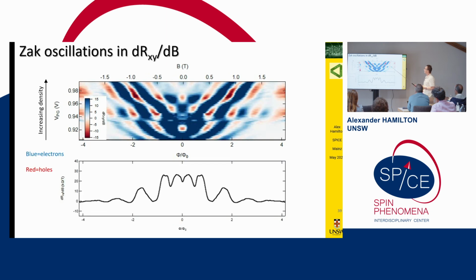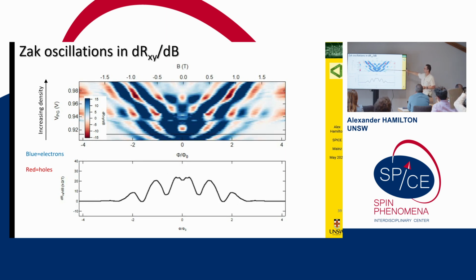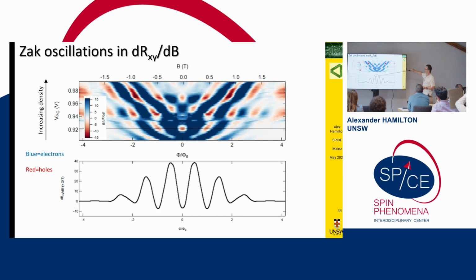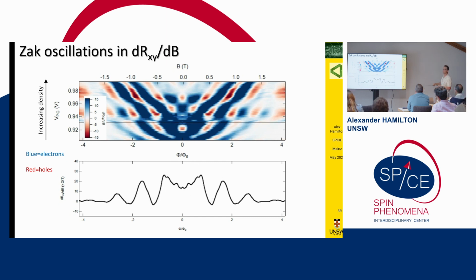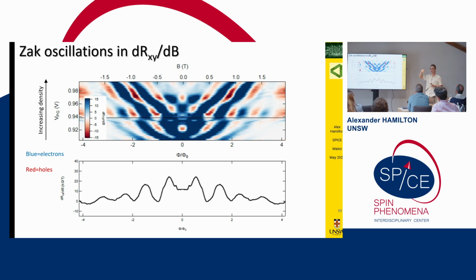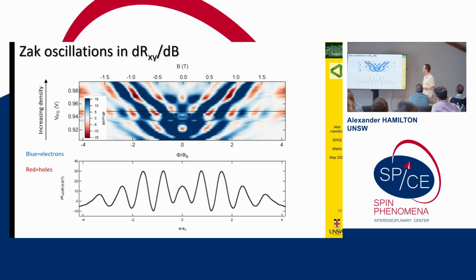You can see it a bit more clearly if I just take the derivative of the Hall voltage as a function of magnetic field. And again, I start down here, and then here I'm plotting the derivative as a function of magnetic field, and I'm just going to sweep the chemical potential up through. And as I sweep the chemical potential, you can just see these beautiful periodic oscillations as I'm threading the flux through the unit cell.